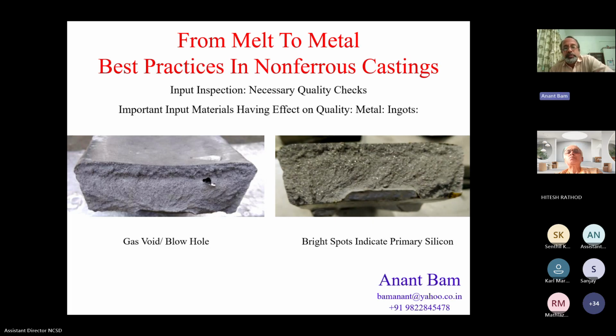The right-hand side picture shows bright white spots. Can everybody see those spots? Yes, sir. Those spots are of primary silicon. It's a metallurgical defect, and it indicates that the silicon is not dissolved properly and is present in an unalloyed state, which is a dangerous condition for casting. The casting becomes brittle at that spot. Also, primary silicon attracts shrinkage voids, and hence discontinuities appear there, and the casting becomes fragile. Next slide, please.